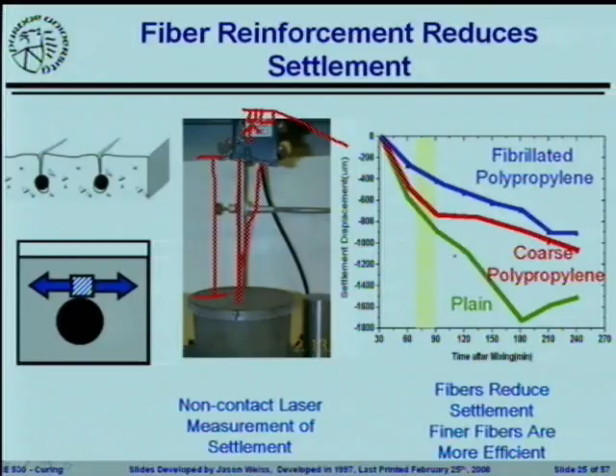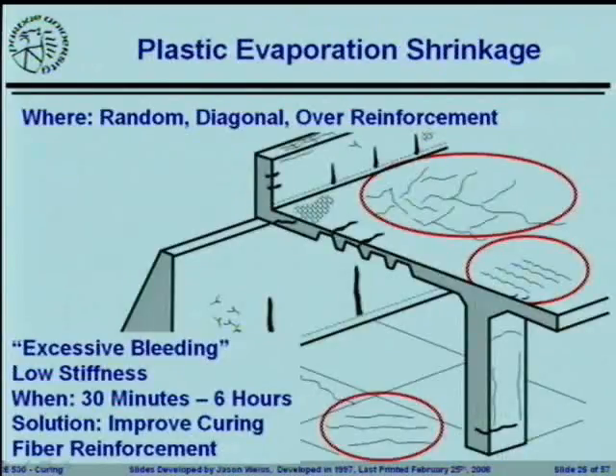Here you can see the effects. We've got a plain concrete. We've got a fibrillated concrete with fibrillated polypropylene fibers. One of the things that the fibers do is they make it a little bit more difficult for the concrete to settle. This is one of the reasons why the fibers tend to work. They tend to help with plastic shrinkage cracking. They really help on the settlement side.